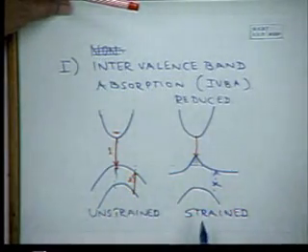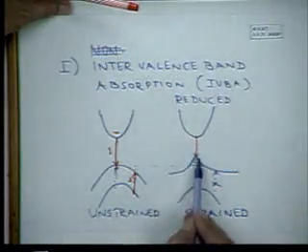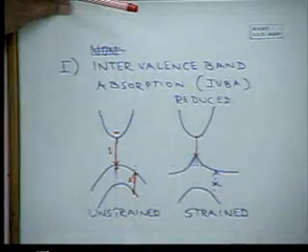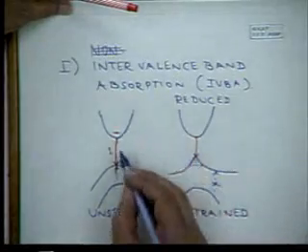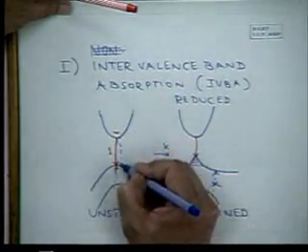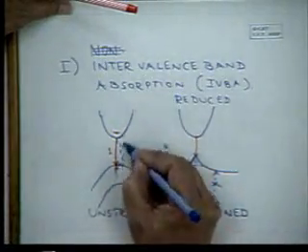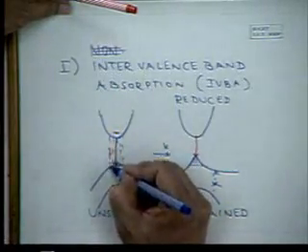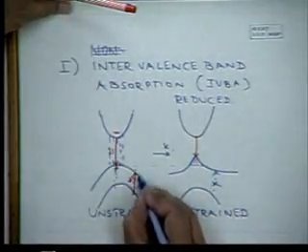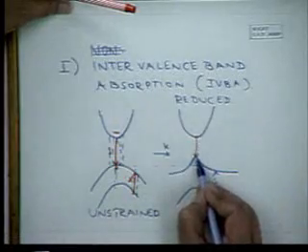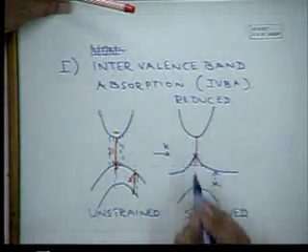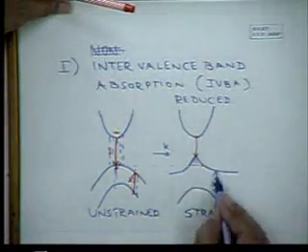This is due to two phenomena. One is this peaking in the density of states here, so that you don't get a variety here. This is E versus K. Here there is a possibility that you get recombination there, so a variety of different energies are possible, and this spread of energies will give rise to absorption there. Here, the probability is limited to a particular energy, and that energy is not sufficient to create this IVBA.